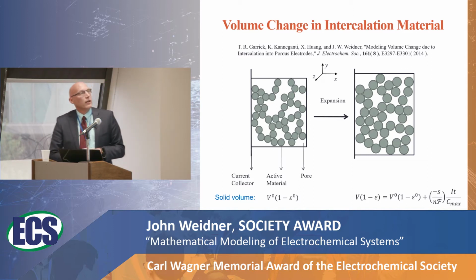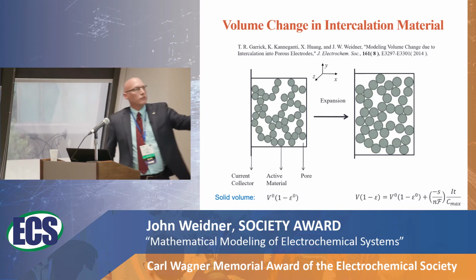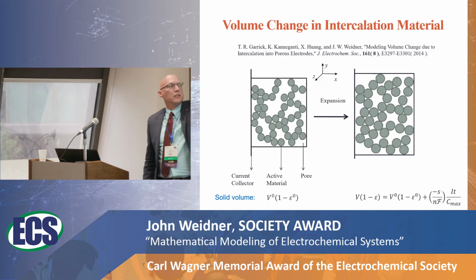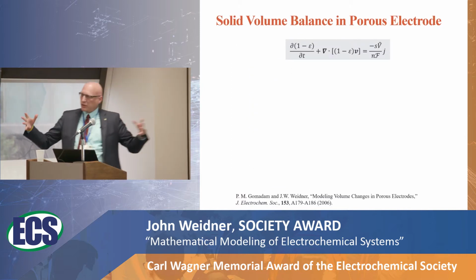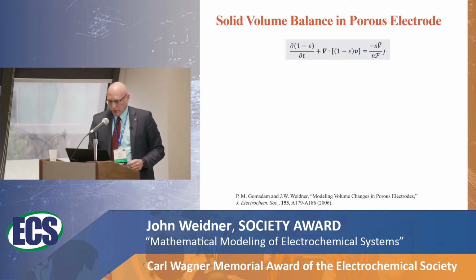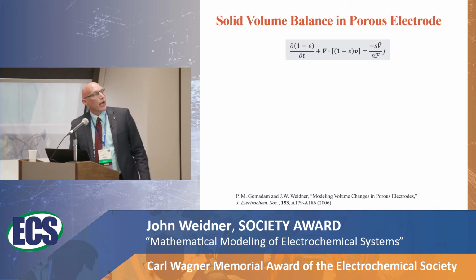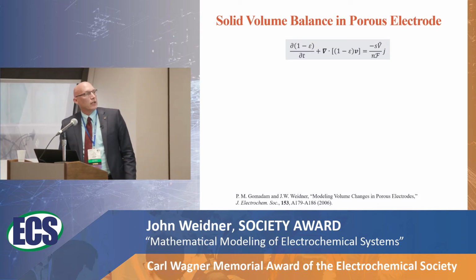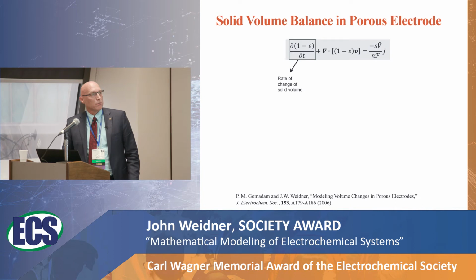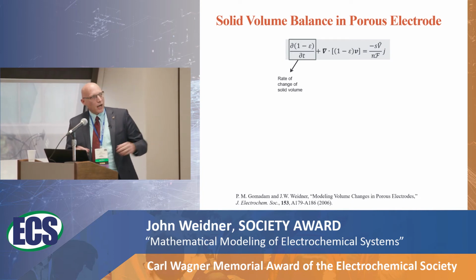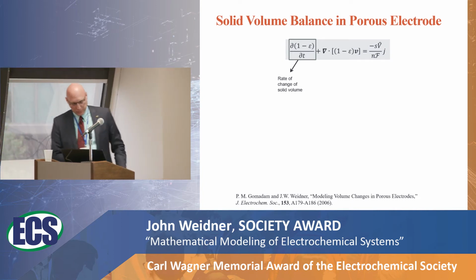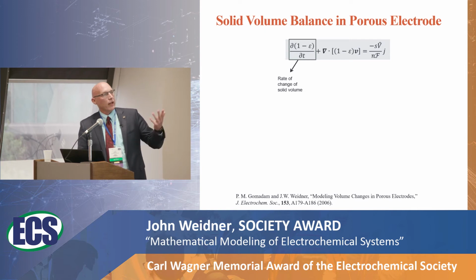And so how do we model that? Well, instead of just relating the reaction rate to the porosity change, we're going to add a velocity term. In other words, the electrode itself is moving. So here we have the rate of change of the solid volume, or in other words, the porosity change, the velocity of the electrode, or the expansion, the displacement of the electrode, and then again, this is the